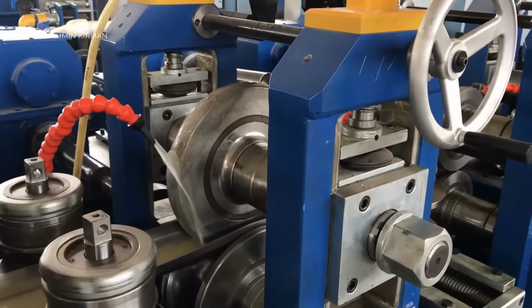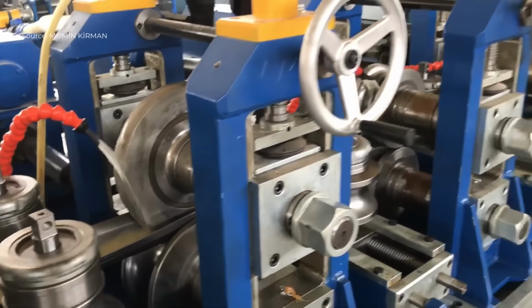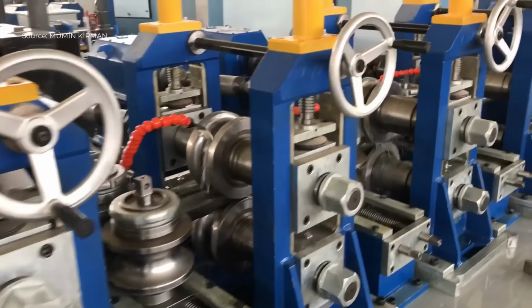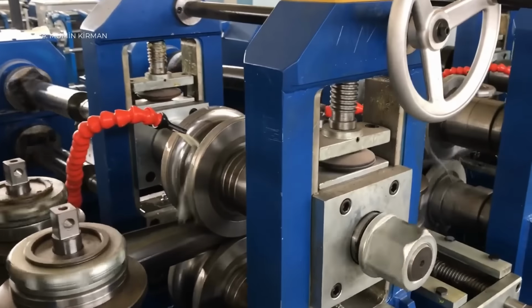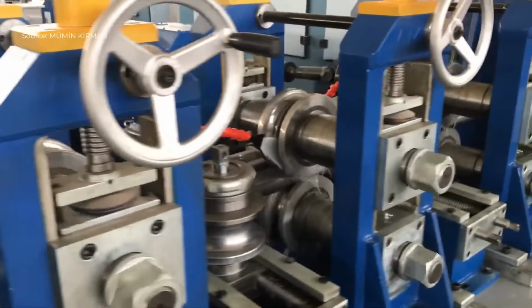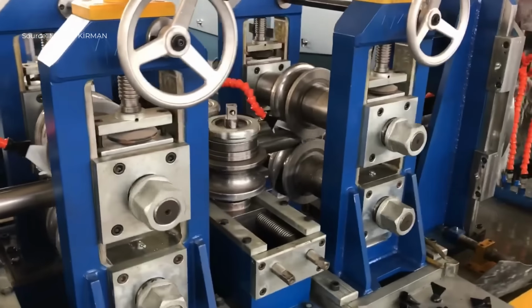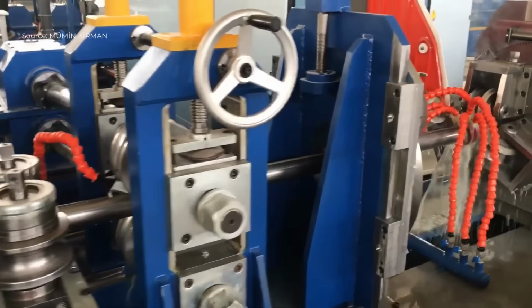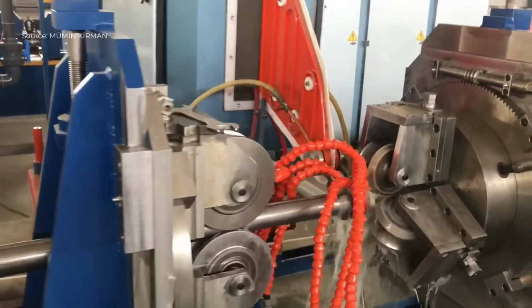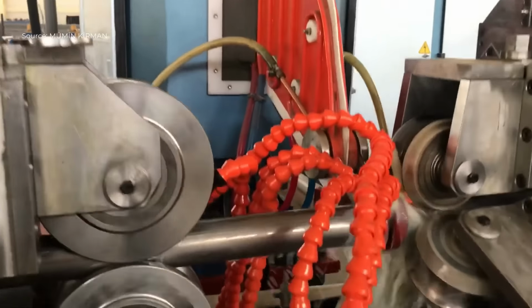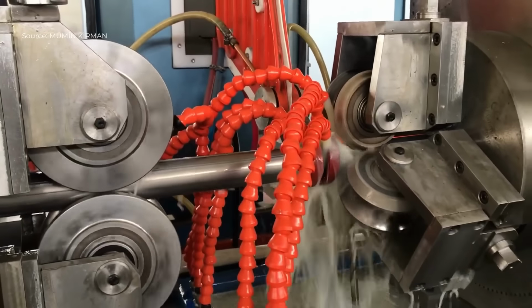Once the edges of the strip are properly aligned, the tube passes through the high-frequency welding station. Here, concentrated electrical energy heats the edges, and pressure rollers forge them together to create a continuous, strong longitudinal weld. Immediately after welding, excess weld bead on the outer surface is trimmed off to achieve a clean and smooth finish.